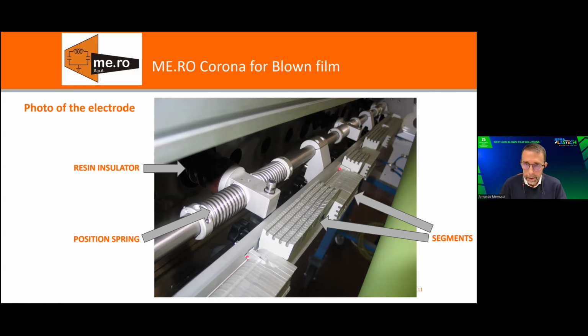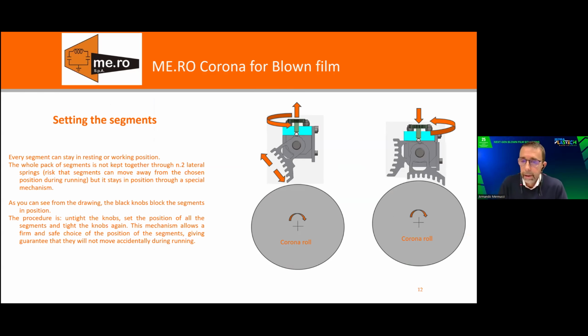Another very important characteristic is the way we set the segments. This is absolutely fundamental because we are the only one having a mechanical stop for setting the segments. What happens is that the operator changes the pattern of the segments. Once he has decided which segments will discharge and which segments will not discharge, it will block everything mechanically. And this is a guarantee that no matter if you produce for 2, 3, 4, 5 years continuously with the same format, after days of production, the pattern of the segments will remain absolutely the same. So no surprise that no segments have fallen down.